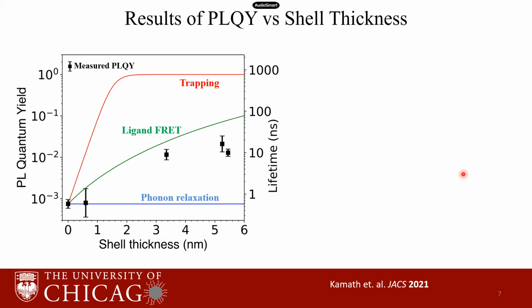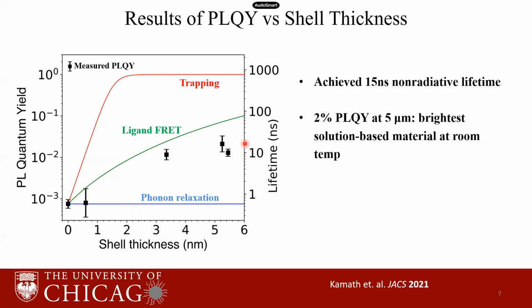Here I have the main results of my work. The black data points are measured quantum yields for core shell nanoparticles with different shell thicknesses. We can see immediately that growth of this thick shell leads to a dramatic increase in the quantum yield, and the non-radiative lifetime corresponds to 15 nanoseconds, which is 10 times larger than the previous record.